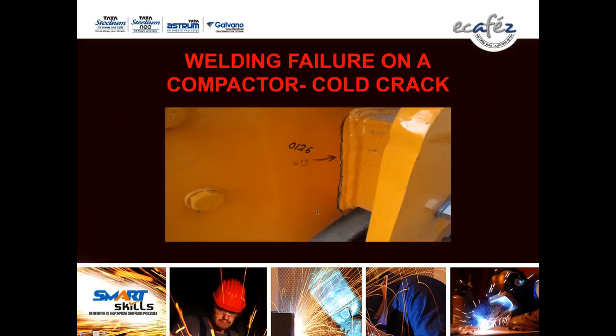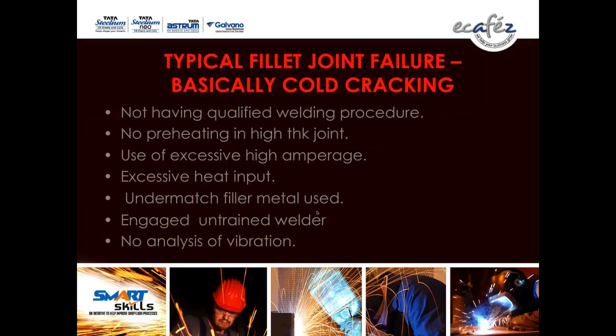Next, welding failure on a compactor, cold crack. See the pictorial view. This is for not having a qualified welding procedure, no preheating in a high thick joint, use of excessive high amperage, excessive heat input, undermatched filler metal, engaging an untrained welder for this job, and no analysis of vibration.